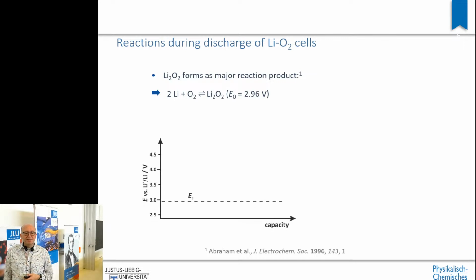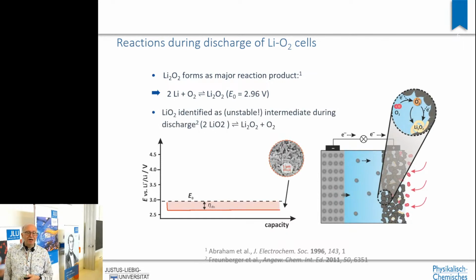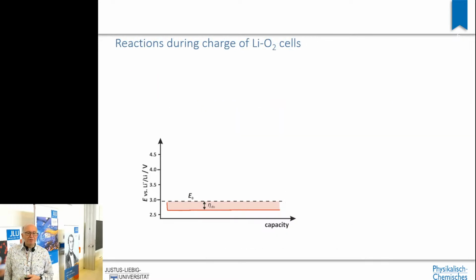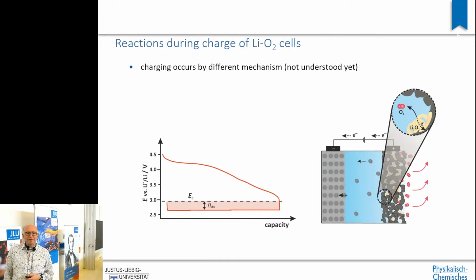So what happens is that we have here a graph where we have the capacity, that means the charge we take out of an electrochemical cell, and on the left axis we have the electric potential. Discharging such a cell, a lithium oxygen cell, is very simple, and you don't have a huge overvoltage, you don't lose much energy, so the loss of energy is relatively small. But charging the cell, so reforming the oxygen molecule, causes high overvoltage. So it's really difficult. It's easy to add electrons to the oxygen molecule in this alkaline environment, but it's difficult to get these electrons back.